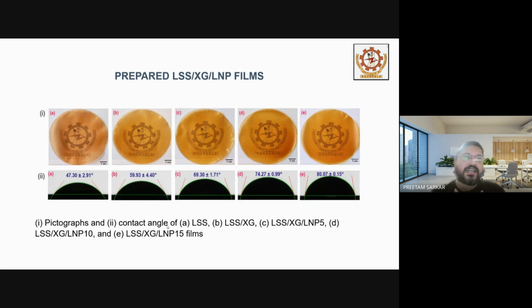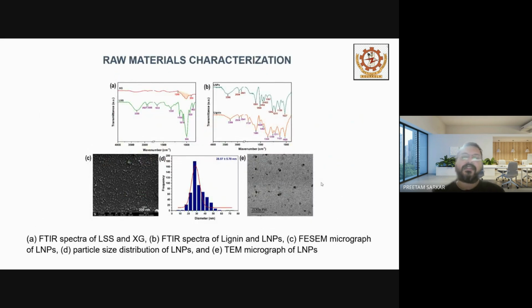Why hydrophobic? Because they want to repel the water molecules, right? So it starts from 47.3 and increases to 80.07, which is significantly different compared to the control. We also do some raw material characterizations. We use FTIR to characterize our raw materials, the raw xyloglucan and the LSS, the lychee seed starch.